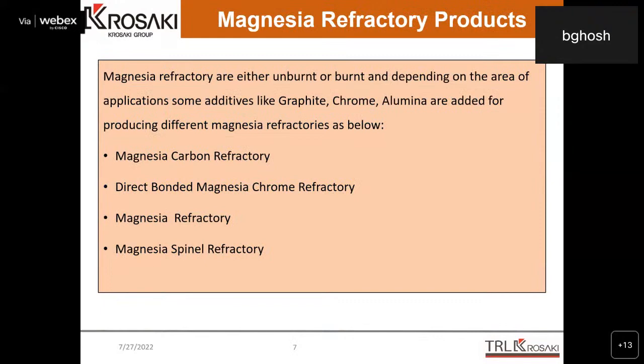And as I have already explained, magnesia is combined with graphite, chromia, and alumina to make different magnesia refractories. Magnesia carbon refractories are predominantly used in the basic oxygen furnace, in the steel ladle, converter, steel ladle slag line areas, and also in the electric arc furnace. So magnesia carbon is a prominent material used by the steel industry.